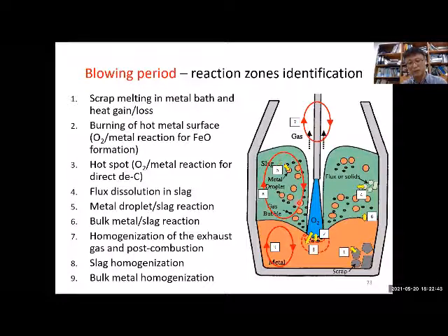And a lot of liquid droplets can be formed. And these liquid droplets travel inside of the slag and make chemical reactions. It's a very, very dynamic process. By using this dynamic process, we can remove the carbon from 5% to 500 ppm within 18 minutes. So it's a very, very violent, very dynamic process. It's almost impossible to do any sampling of the data inside. So this is kind of a black box process so far.